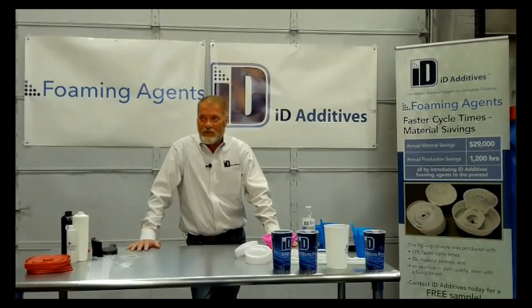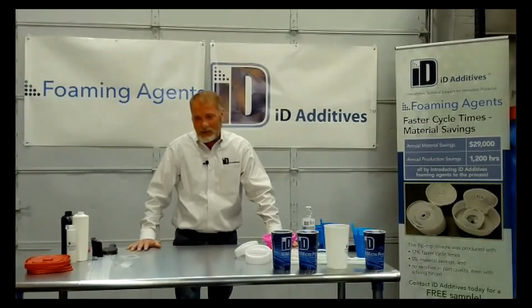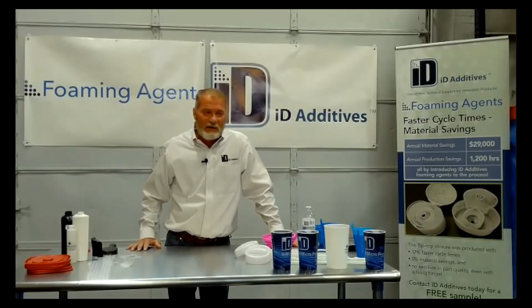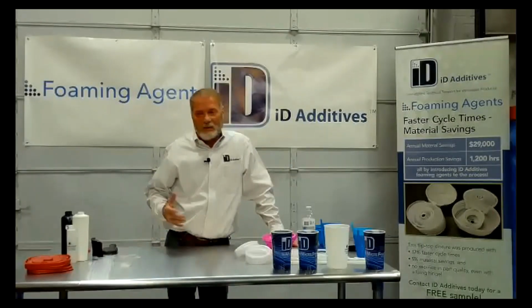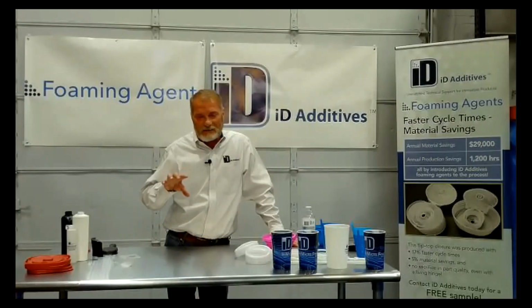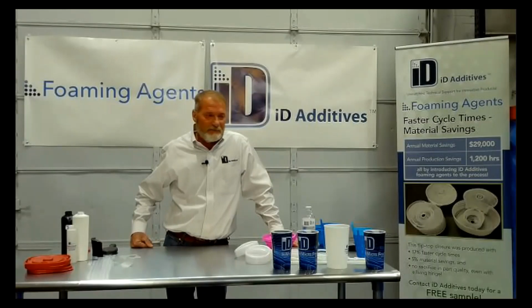We have another question before opening it up even further. For unfilled nylon in an injection molding application, 1 inch thick part, what do you think is the maximum density reduction that can be achieved? So I think you can hit about, with the 71896, really not changing a lot, you could probably hit about 3.5%, 4%.